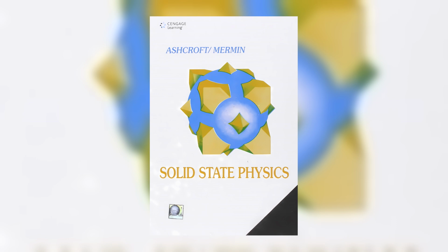The sign of the curvature partitions the phenomena. Energy that rises with the field gives diamagnetism, where the susceptibility is less than 0, closed shells resisting flux, the Larmor response. Energy that falls with the field gives paramagnetism, where the susceptibility is greater than 0, moments aligning, the Curie response. Diamagnetism and paramagnetism are two signs of one piece of bookkeeping. Ashcroft and Mermin's move is to fix that thermodynamic scaffold first, so every later case, atomic shells, free ions, conduction electrons, is simply a matter of which energy you differentiate.